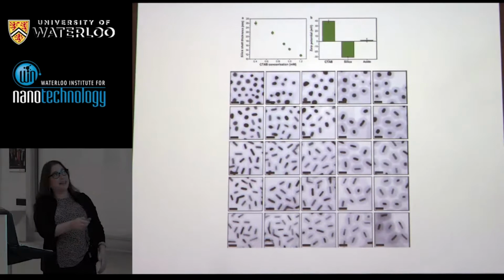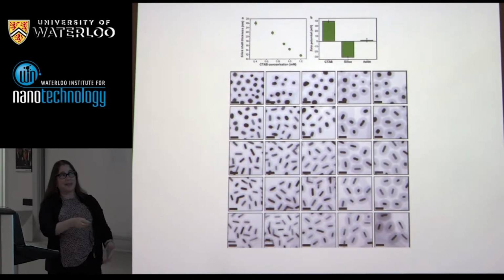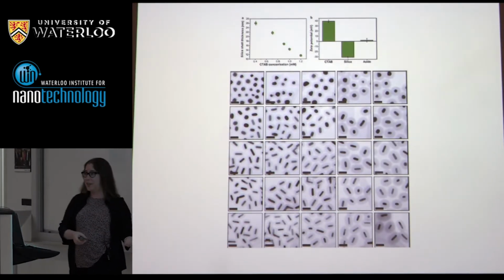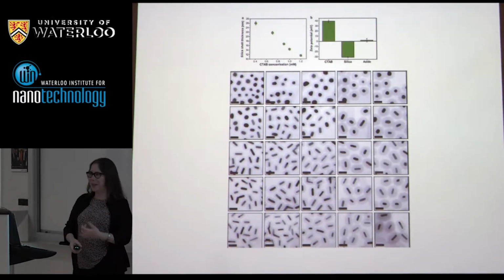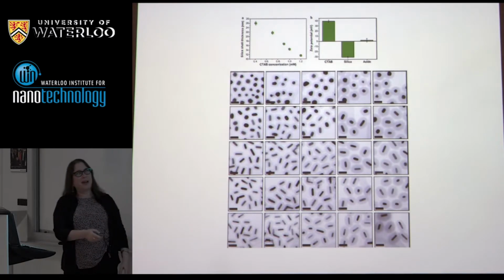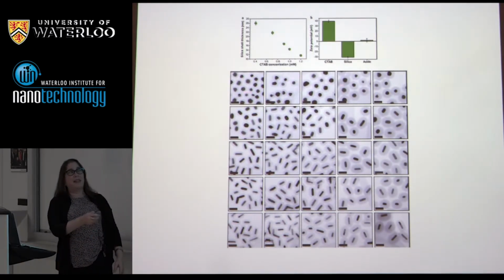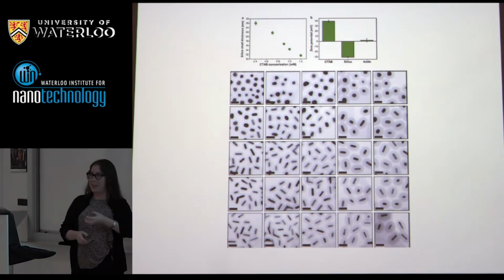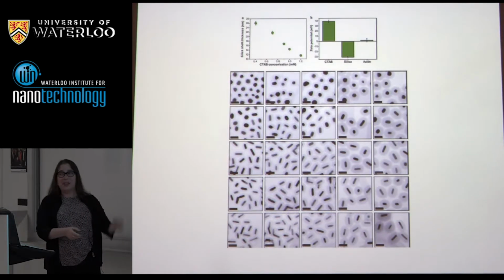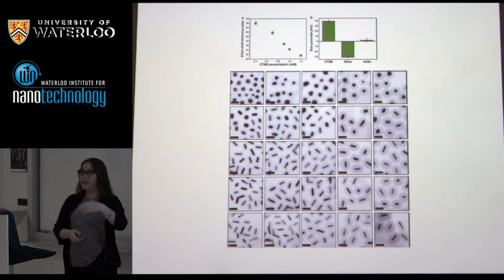And then the spacer layer silica, now this was another place where things that look like they work in the literature actually are a little tough. Even we have a paper long ago of putting silica on gold nanoparticles, although of just only one thickness. The problem here is that these are mesoporous silica shells, and the CTAB that's on the particles is actually going to be the template where we're going to hydrolyze and condense silica around that on the particle, which is a little tricky. And it turns out you really need to know your CTAB concentration to do this well because the outer leaflet is on, off, there's dynamic equilibrium.